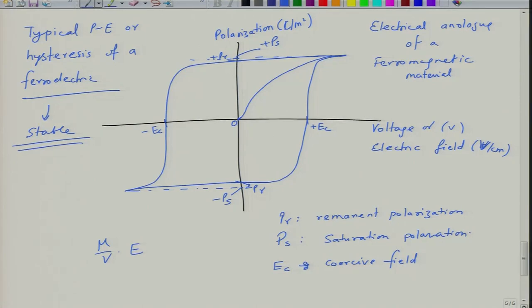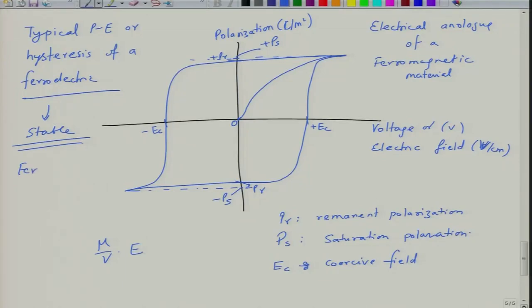There is another class of materials called electrets, in which this phenomenon is transient, it is a temporary phenomenon. You will see in electrets also a similar sort of loop, but that is not stable as a function of time. So do not confuse, a ferroelectric is not an electret. A lot of electrets also tend to show similar loops, maybe not of very good quality, but they show a hysteresis between polarization and electric field, but that is not a permanent behavior. This is a permanent behavior, as long as your temperature is below a certain temperature.